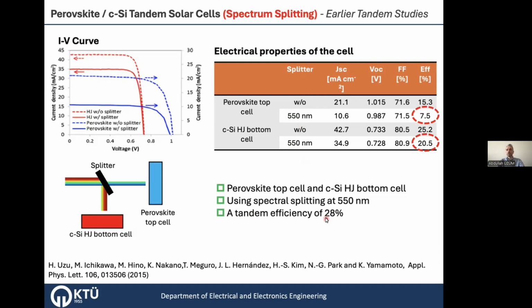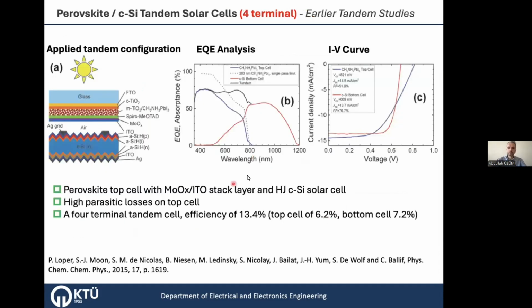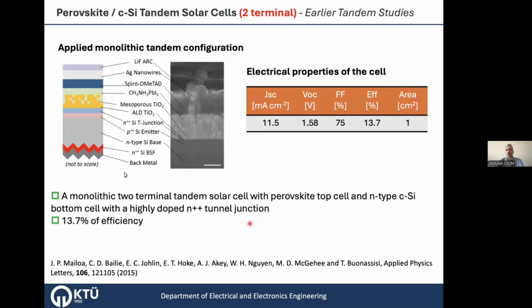And again, earlier tandem studies, this is the example for 4-terminal studies. They used a similar mesoscopic top cell and silicon heterojunction bottom cell, like we did. In this case, they used molybdenum oxide as the recombination junction. Even if it is stuck together, you need a conductive layer for the recombination, right? That's why they use molybdenum oxide here and ITO on here with the silver grids. And this is 4-terminal. That means they have the efficiency separately and they add it together. But with filtering, they had, again, 13.4% efficient solar cells.